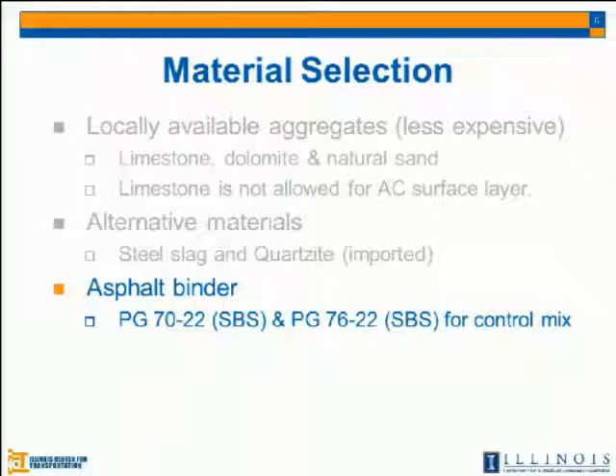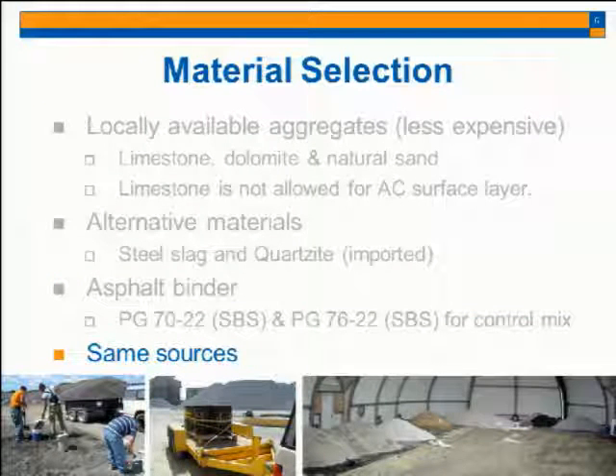The asphalt binder used in this project is PG70-22 and PG76-22 SBS modified binder. To minimize variation from other sources, even though we use the dolomite, if we sample the same dolomite from two different sources, we might have some variation because of the source. So we sampled all the aggregate used in the control mix and the new mixtures from one plant. So I think we minimized the variation of the aggregate from different sources.